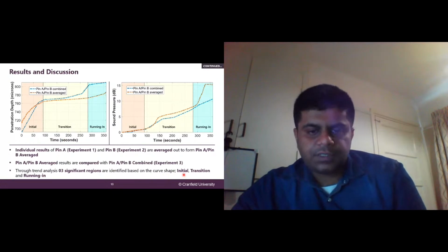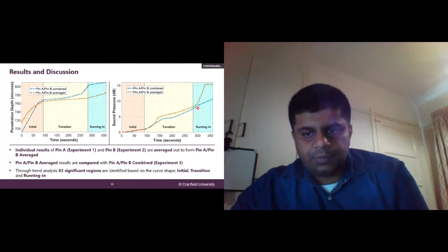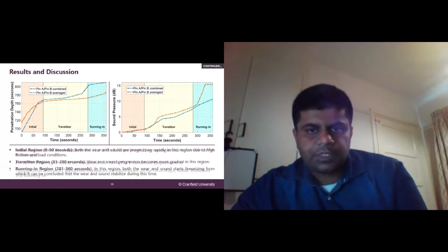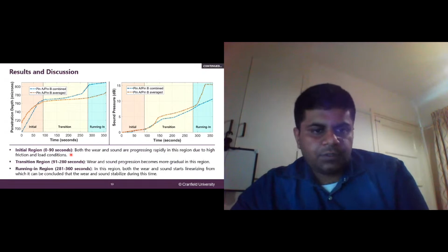The three regions, initial, transition and running in, are identified based on the change in the graph shape. So these are not really a specific quantity that you can pick out and fix at a particular time, but based on the graph changes, this is being plotted for this particular experiment. So the initial region is from 0 to 90 seconds. Both the wear and sound are progressing rapidly in this region.